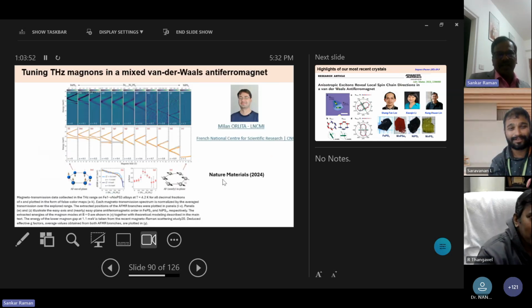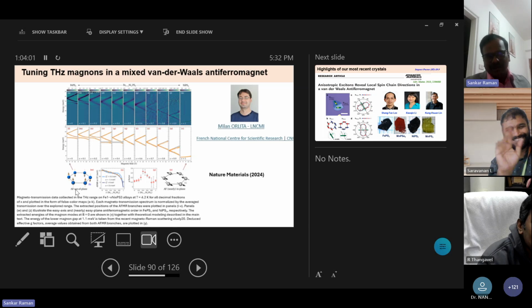And recently I already informed, right, NiPS3 belongs to antiferromagnetic out of plane, clearly shown from the left hand side, and antiferromagnetic nearly in plane for NiPS3. We checked with the terahertz magnon using high magnetic field optical measurement, and recently this material was accepted for Nature Materials.